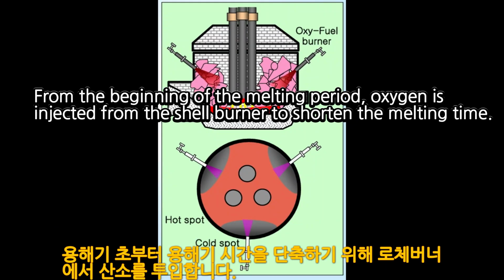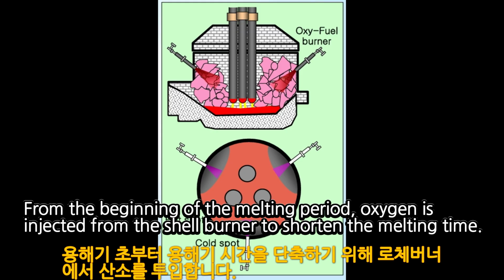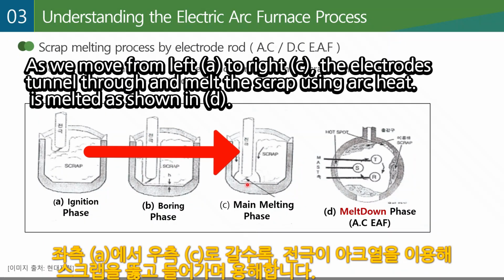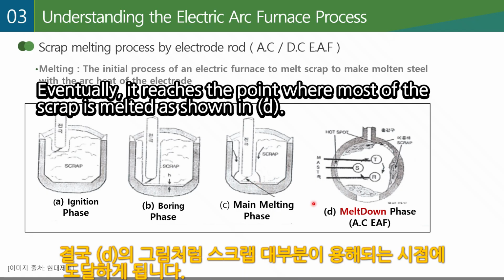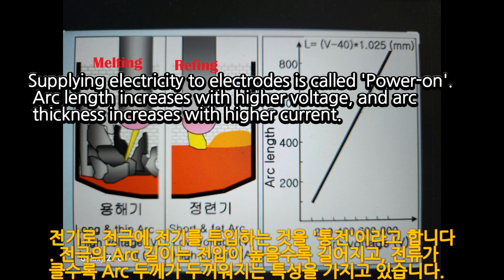From the beginning of the melting period, oxygen is injected from the shell burner to shorten the melting time. As we move from left A to right C, the electrodes tunnel through and melt the scrap using arc heat. Eventually, it reaches the point where most of the scrap is melted as shown in D. Supplying electricity to electrodes is called power on.